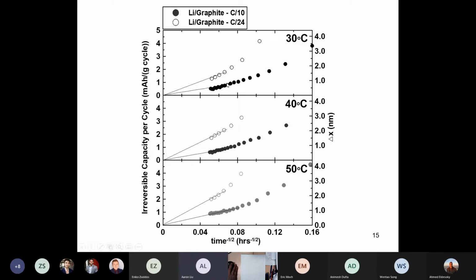Yeah, that's exactly right. Okay, so at C over 24, you're spending 48 hours for a charge discharge cycle. And during that entire time, the reaction between the lithium at the surface of the graphite and the electrolyte is occurring. So you get basically 48 divided by 20 times more irreversible capacity per cycle. So about a factor of 2.5 times more when you are going at the lower rate compared to the higher rate. It's just a question of time.